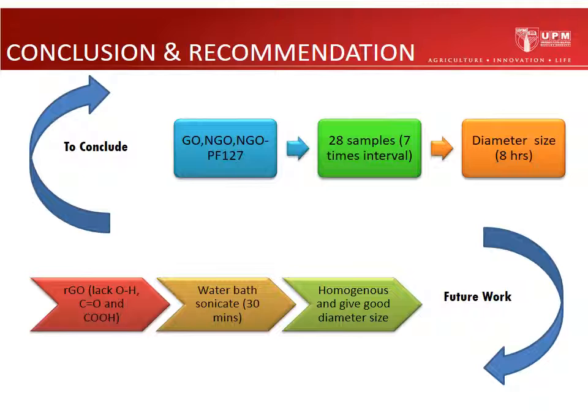Okay, so instead of using NGO, we can actually use RGO because it lacks OH, C double bond O, and COOH, and RGO is less toxic compared to GO. To make sure the diameter size of the nanoparticles is still in nano size, we need to use a water bath sonicator for about 30 minutes or more, so the size will become homogeneous and give a good diameter size.